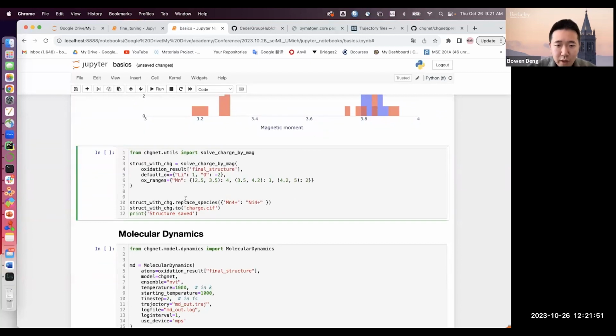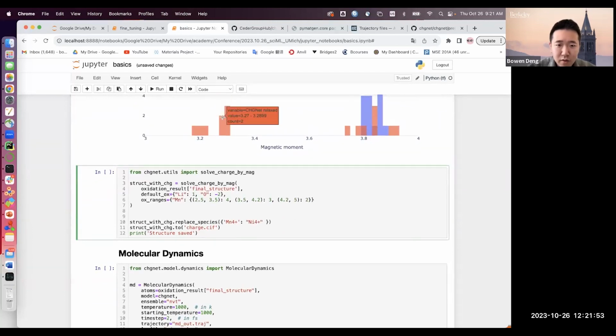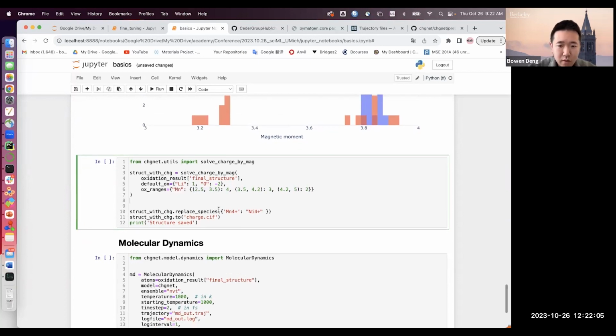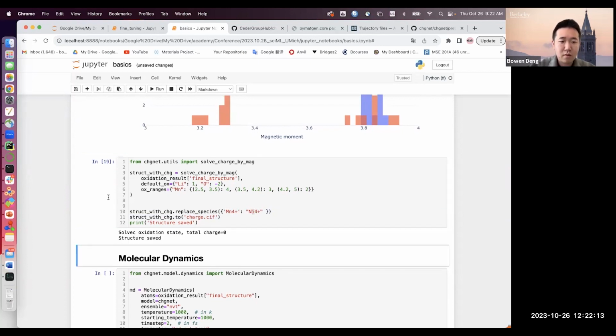And how do we actually apply these magmoms and transform them into charges? You can use this function. You assign, for example, 2.5 to 3.5 magmom to 4 plus, and 3.5 to 4.2 to 3 plus. And for better visualization, I'm replacing the 4 plus atoms with nickel 4 plus, so that I can save the structure. And let me show you what the structure looks like.